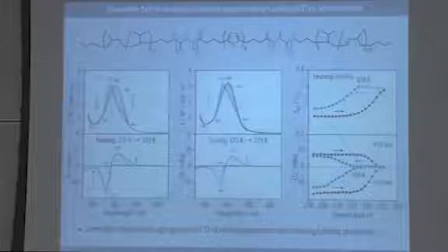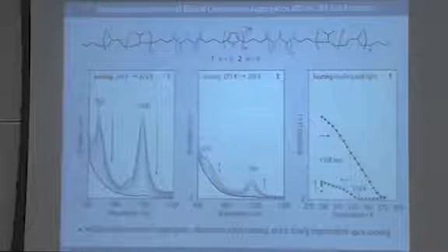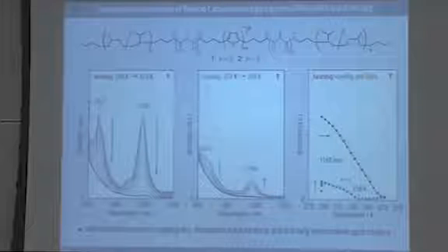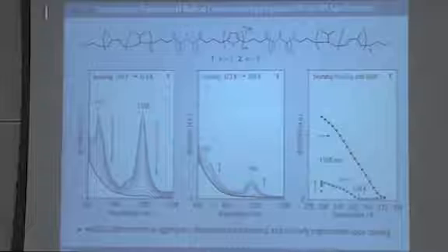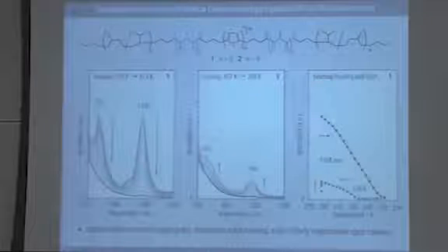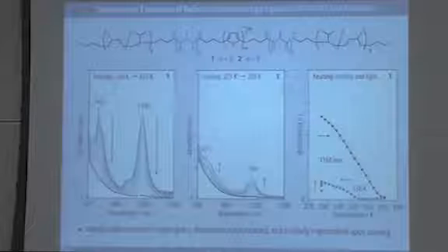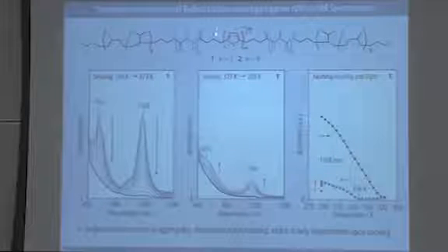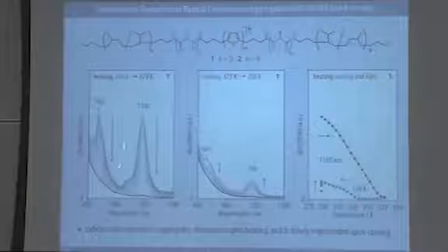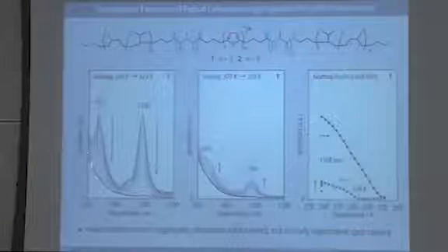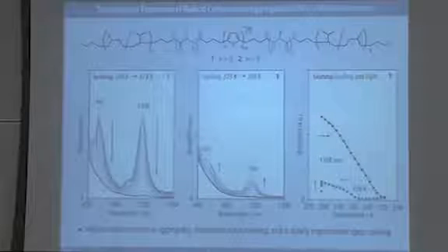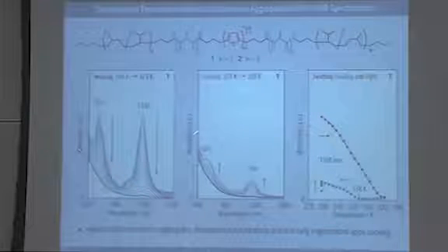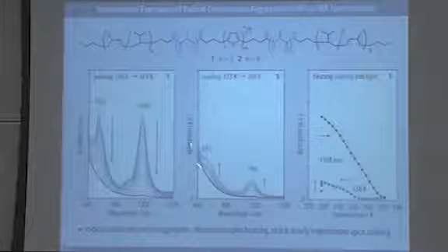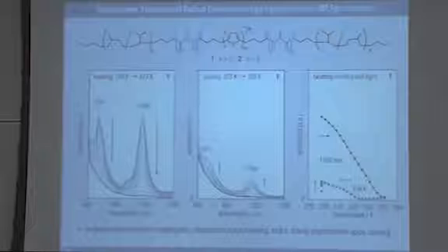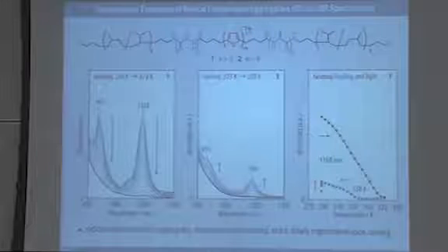But what we noticed at the same time is that in addition to this main UV-Vis absorption, we see two additional bands of relatively high intensity compared to any other system in the literature. So this is about 1/10 of the height of the main optical absorption, in the red and near infrared region. And these peaks are actually typical for a quaterthiophene radical cation. And as you can see, these peaks completely disappear as we heat the solution and deaggregate the nanofibrils. And as we cool the solutions and reassemble the nanofibrils, these peaks slowly come back up, even in the dark, even under careful exclusion of oxygen.